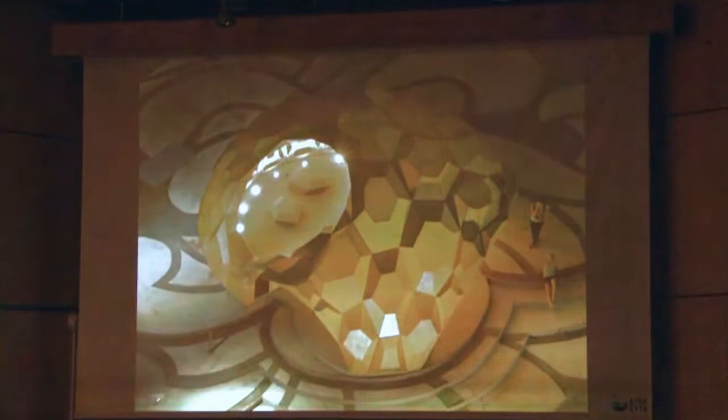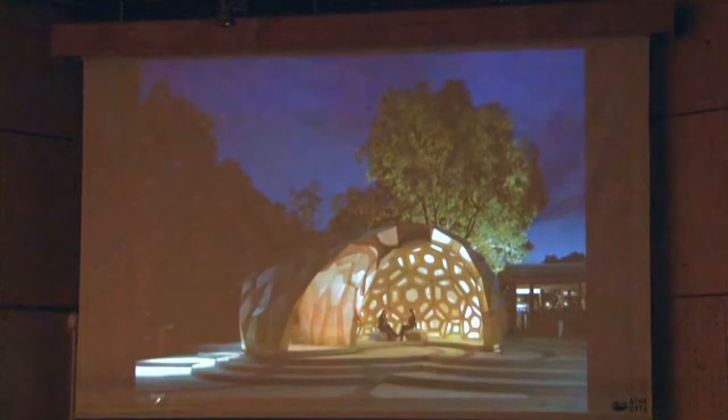could be built using, again, extremely thin plates. So all the plates, without any exception, in this structure have again a thickness of only 6.1 millimeters, which means you get an extremely materially efficient structure that manages to enclose more than 200 cubic meters of space with only 2 cubic meters of wood. And I think you get an impression of the kind of architectural result, which actually turned out to be an extremely popular site for all kinds of informal urban activities.